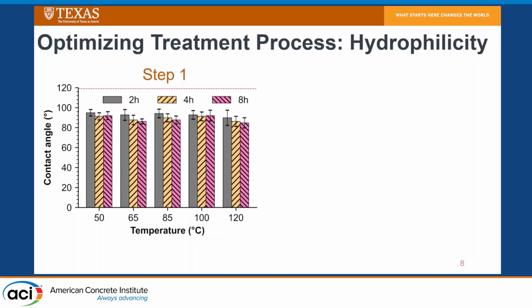And the key thing here is that we thought they were all pretty similar. The lowest contact angle measurement was around 85 degrees using 120 degrees at 8 hours. However, when we looked at 65 degrees at 4 hours, it was very similar. It's like two degrees different. So we decided to use 65 degrees Celsius at 4 hours just in terms of trying to optimize time as well as energy when you start thinking about heating something at 120 degrees for an extended period of time.